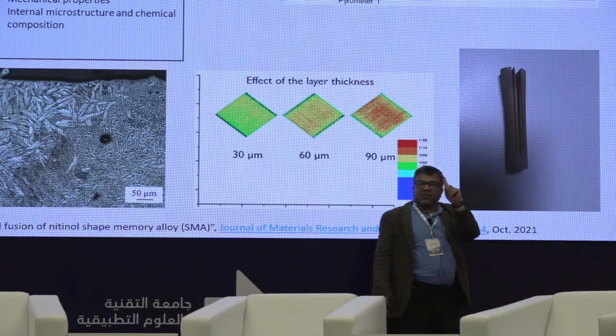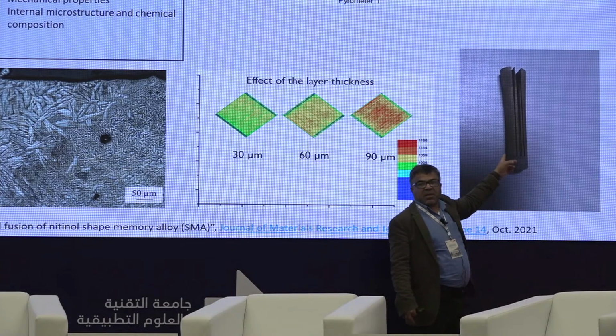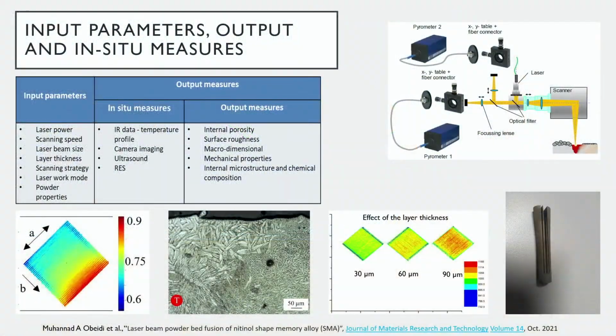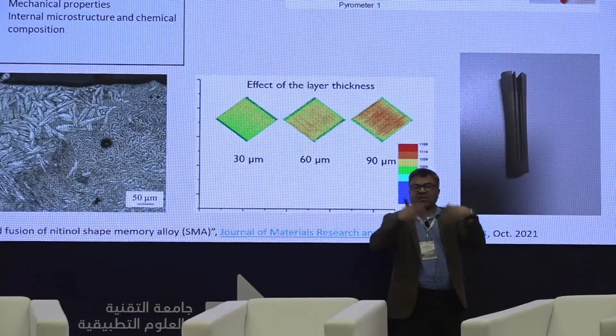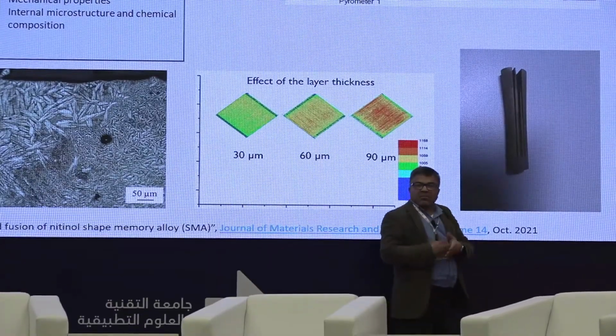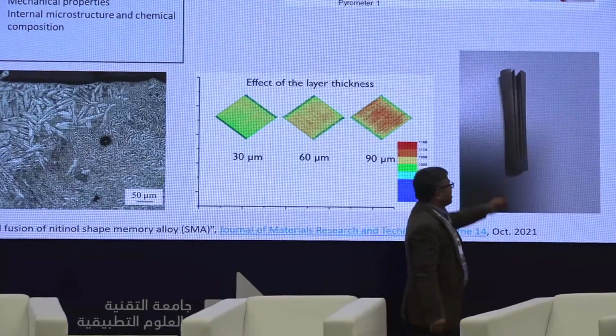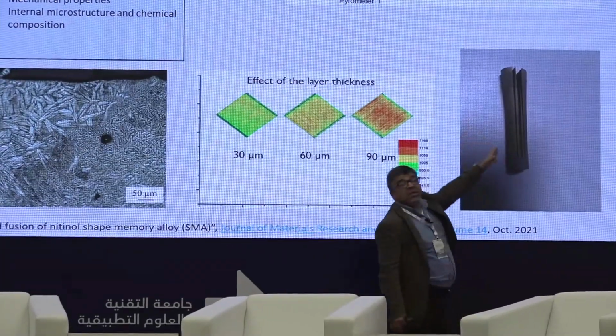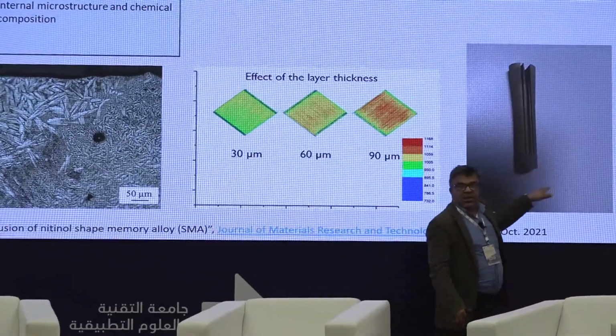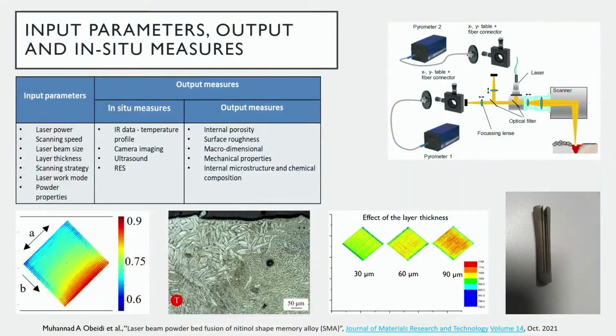So this was just a pin of 10 millimeter diameter, 60 millimeter length. I sliced it just to prove and measure the stresses, residual stresses, thermal residual stresses. While I sliced it using the wire EDM, the sample was diverging like that. And that's the function or indication of anisotropic stresses inside the part. Here, more stresses than there because of the high cooling rate. The surrounding here is still cold, but the surrounding there and the mass of the part itself is being bigger and bigger, so it can store more heat. So there was less thermal stress on top.